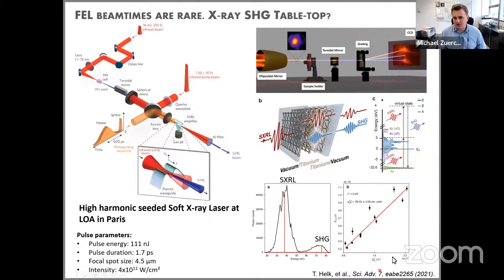Here we plot the square of the inbound intensity, and here we plot the second harmonic response. When we plot this squared over linear, it gives us a linear response, so it's actually quadratic. That was the first demonstration that indeed, with tabletop sources, this is still a fairly big laser system, but it's not inconceivable to reach at least tens of nanojoules with conventional high harmonic sources alone.